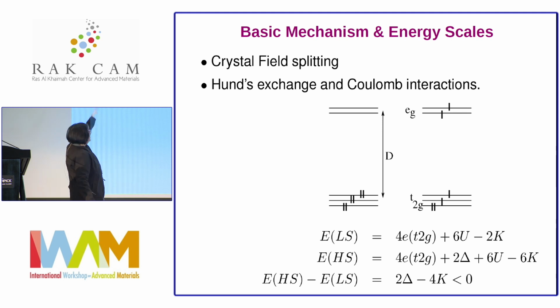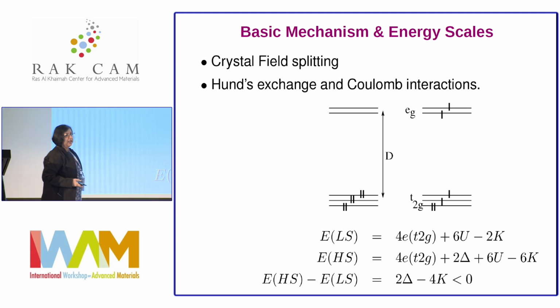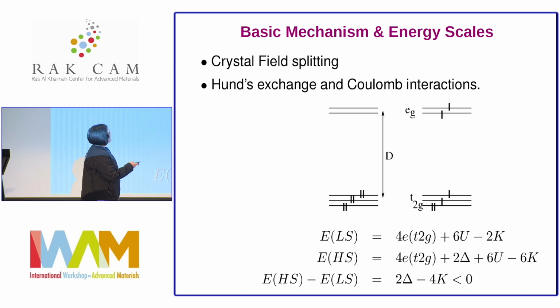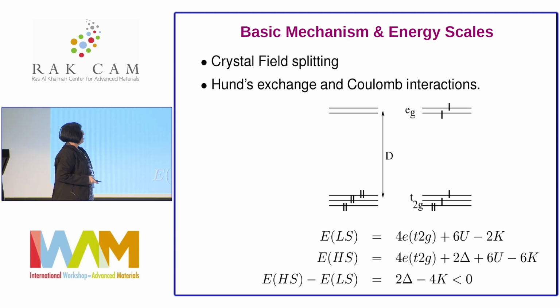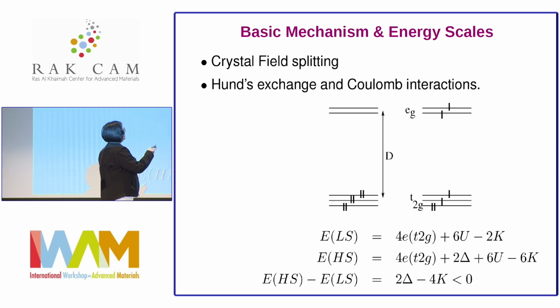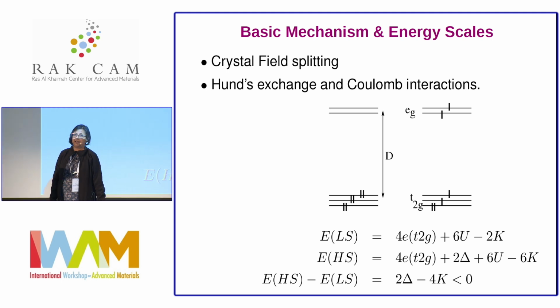Well, so this is the basic energy scales behind such spin crossover phenomena. First is the octahedral crystal field splitting, and the second one is basically the Hund's exchange. Because at the low spin state, if you take the example of iron 2+, all the 6 d electrons are at the t2g state, while in the high spin state, you have to overcome this octahedral crystal field splitting and put 2 of the electrons at the eg state. Of course, this is energetically expensive, but it is helped by the Hund's rule coupling, because in this way you maximize the spin. So these are the energy scales at the molecular level.